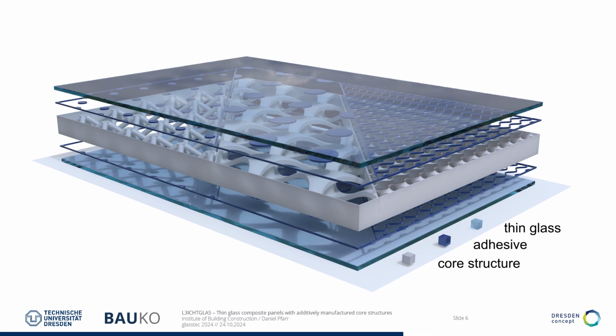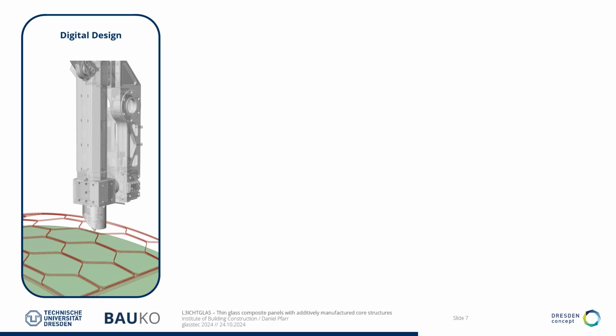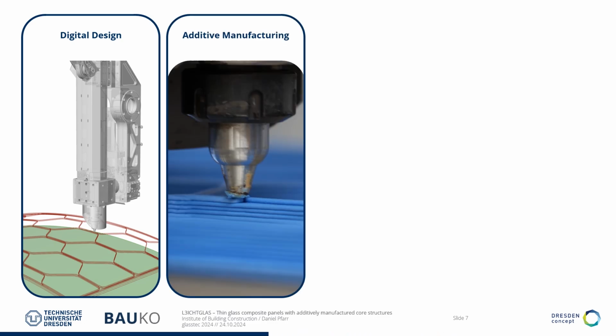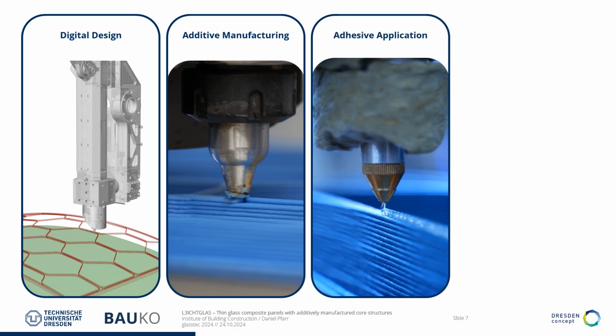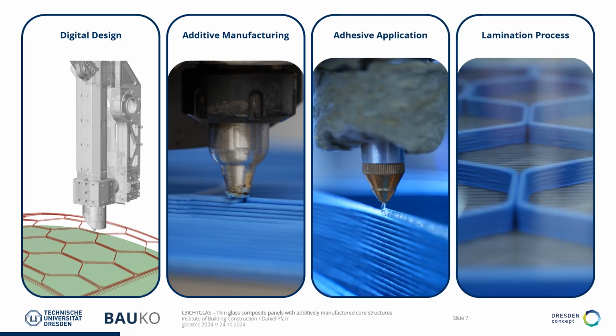So you can see the two very thin sheets of glass, and in the middle, the 3D printed core structure, which can be adapted to a certain use case, and the adhesive joint, which helps us to reach the sandwich and composite effect in the very end. And in the following, I would like to present a little bit of the production process, which starts with a digital manufacturing process in the very beginning, then followed up by a 3D printing process, the adhesive application, and in the very end, the layering and the lamination process.